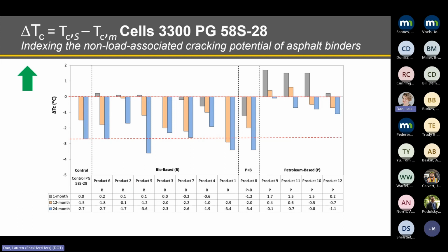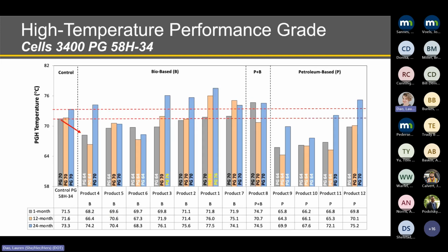Here we have the results for the polymeric surface that contains a PG58H-34. We see similar trends to those observed for the PG58S-28. However, an interesting finding can be seen here, especially for this polymeric surface. We can capture that some of the products really start to have a peak of action at a longer time after application compared to the neat pavement surface. You can see, for example, product 6, product 4, and product 9, that their impact in softening the asphalt binder was captured after 12 months of field application.